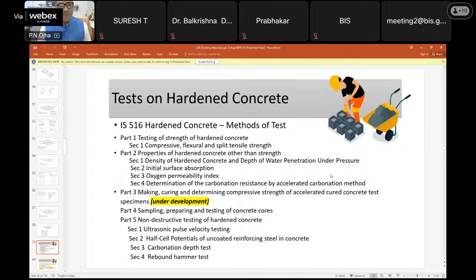We have UPV, part 5, section 1, ultrasonic pulse velocity testing, in which velocity criteria are given for different types of aggregate and concrete, and when the concrete is to be called excellent, good or poor. And then half cell potential. This is a test for concrete structures, particularly aged concrete structures, when some doubt is there that the reinforcement inside the concrete is going through corrosion, and the chances of corrosion we can predict by doing this half cell potential test. And up to what depth the carbonation has happened can be measured, and this test is called the carbonation depth test.